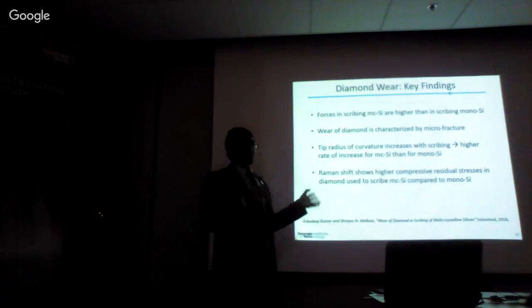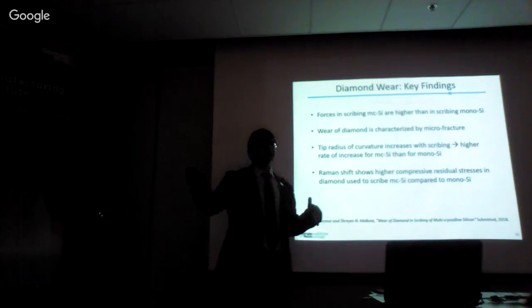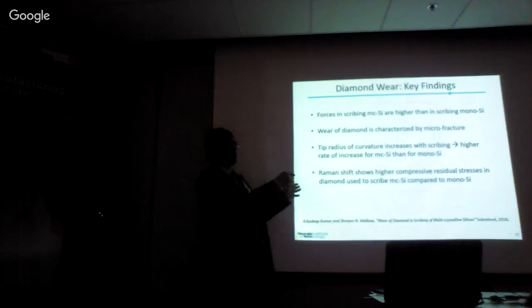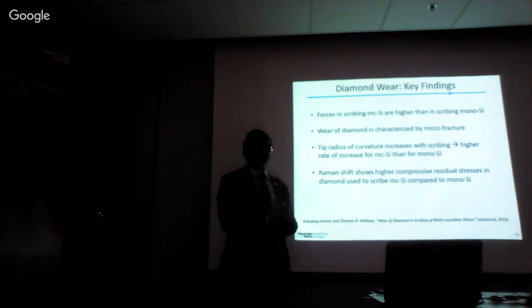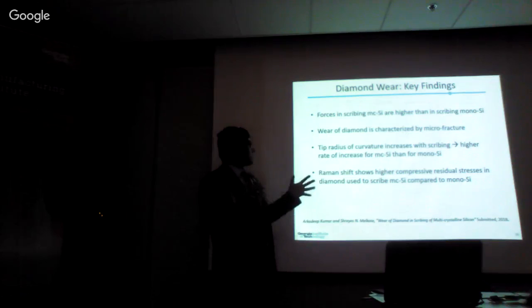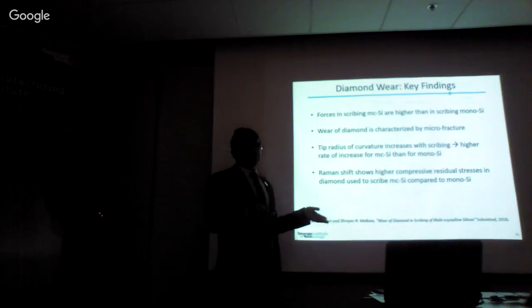process. The tip radius is increasing at a higher rate for multi-crystalline silicon compared to monocrystalline silicon, consistent with the higher forces we see for the multi-crystalline silicon scribing, and the Raman shift shows higher compressive stress.